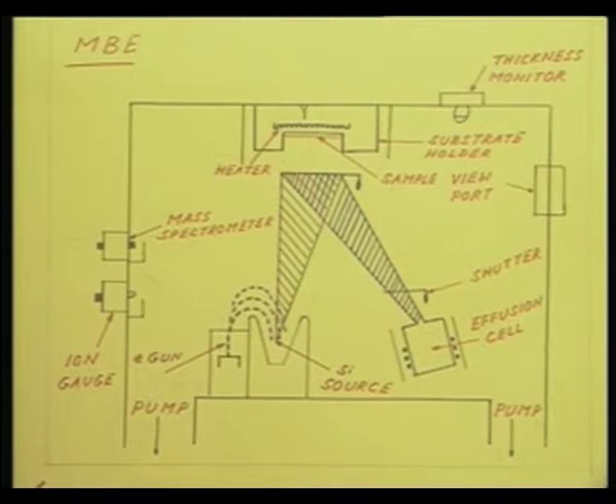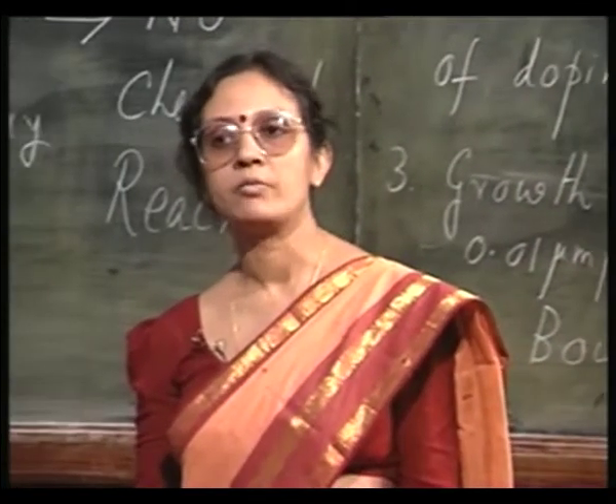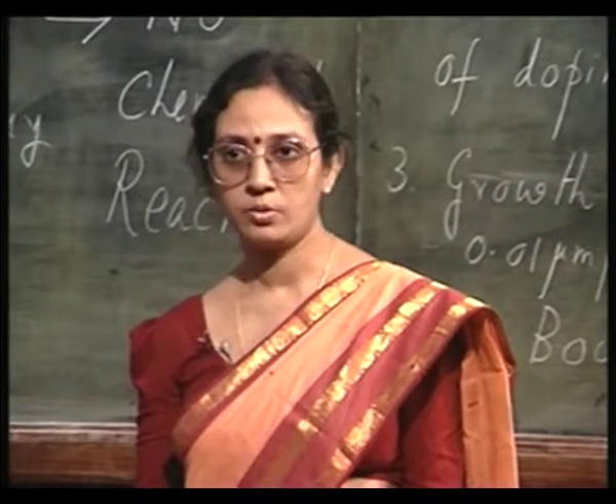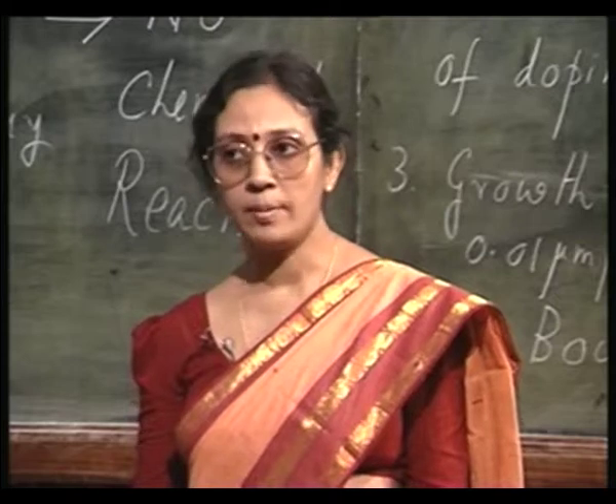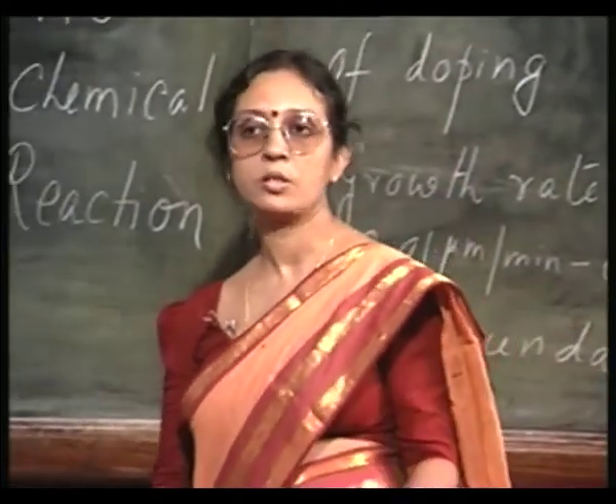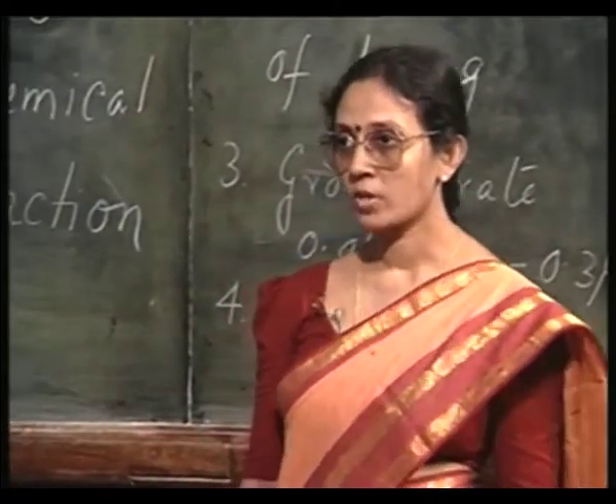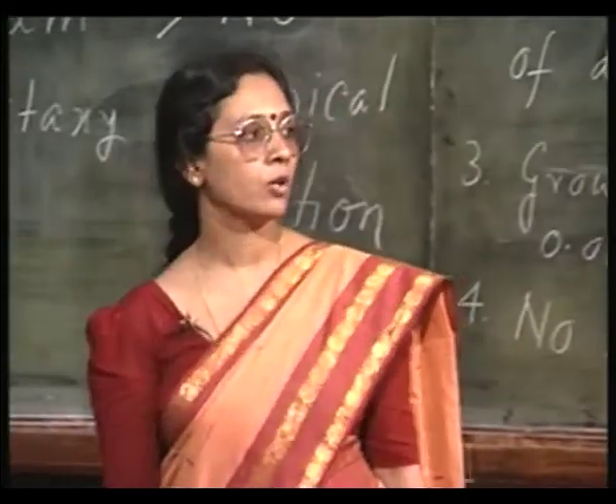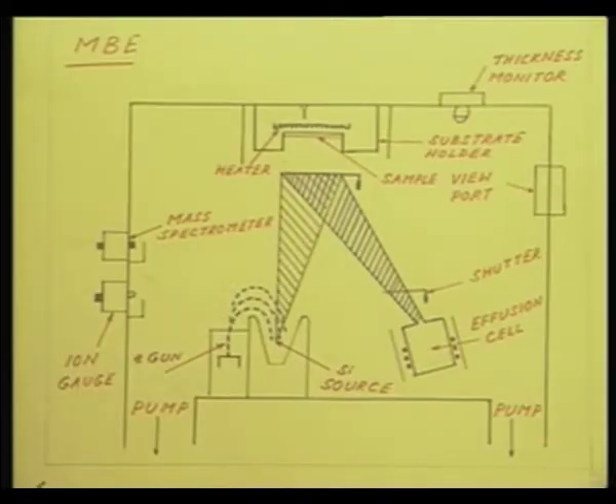Commonly, when we are not talking about ultra high vacuum, the type of pumps we use for a simple thermal evaporation system, for example, that will be rotary pump and diffusion pump. Now, both these pumps use oil, particularly diffusion pump. For MBE, therefore, one should not use the diffusion pump because of its oil vapor. So, usually it is a combination of various pumps like say turbomolecular pump, then cryo pump or ion sublimation pump, something like that. More sophisticated pumping system is required to achieve this very high vacuum. Usually, as I said, a combination of pumping system.